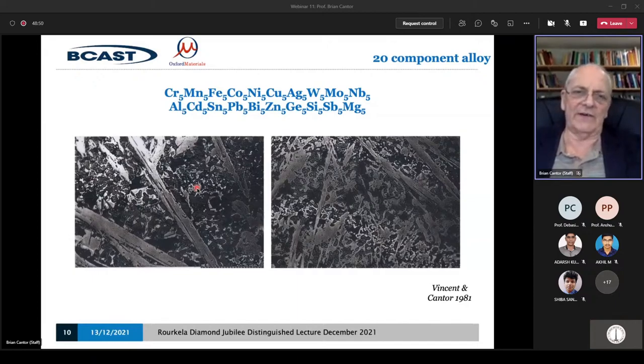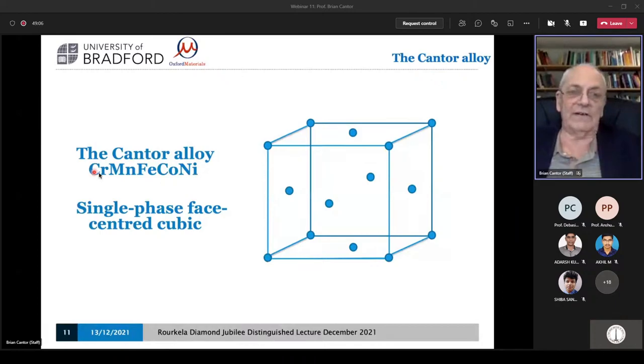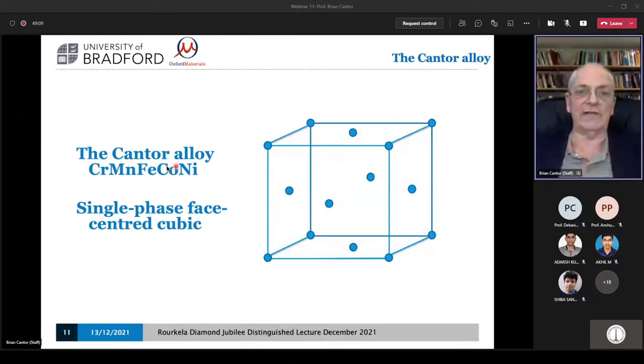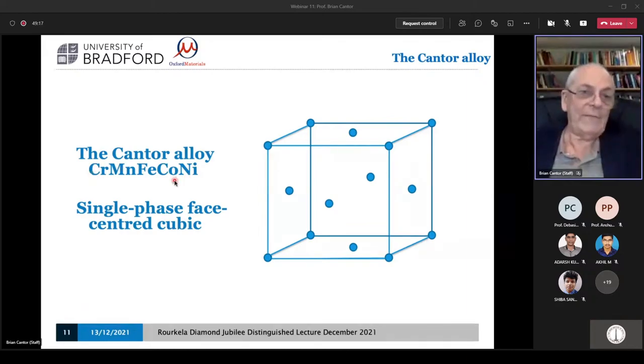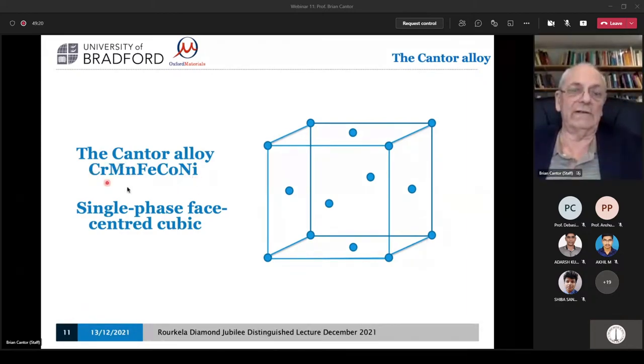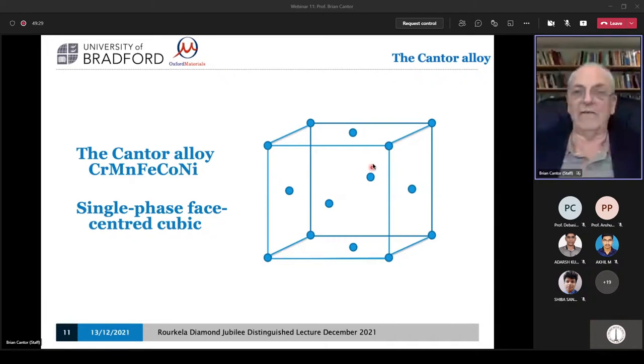But the second discovery, very quickly, was everyone was wrong, because this background black phase here turns out to be what's now known as the Cantor alloy and has become very, very famous. And the Cantor alloy, it turned out, that region of that material consisted of just five components, chromium, manganese, iron, cobalt, and nickel, mainly five components, in equal proportions, 20% of each. So we then made up this alloy, the original Cantor alloy. And this material turns out to have a single phase face-centered cubic structure. That means that the atoms are arranged in a face-centered cubic array.